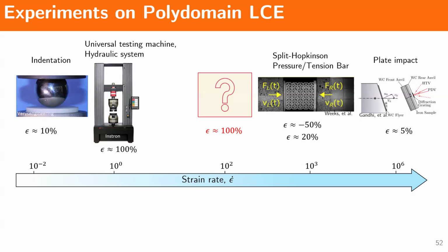So one can think of using an Instron, for example, your typical MTS or Instron hydraulic machine. Now you can probe high strain behavior, but usually it's pretty low strain rate. Then you can go to the other end and do split Hopkinson experiments on these materials. This gives you large strain rate, but the strain that you get, because of the nature of these experiments, is usually pretty low. We're interested in probing deformation under large strain rate and also large strain, because the soft behavior we get is really the soft mode under very large strain. So we want to capture that here.